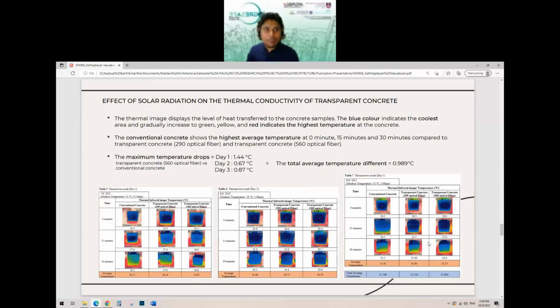And second is the effect of solar radiation on thermal conductivity of transparent concrete. The thermal image displays the level of heat transferred to the concrete sample. As we can see in the table below, the blue color indicates the coolest area and gradually increases to green, yellow and red, which indicates the highest temperature of the concrete. The result shows the conventional concrete has the highest average temperature at 0 minutes, 15 minutes and 30 minutes compared to transparent concrete with 290 optical fibers and 560 optical fibers.